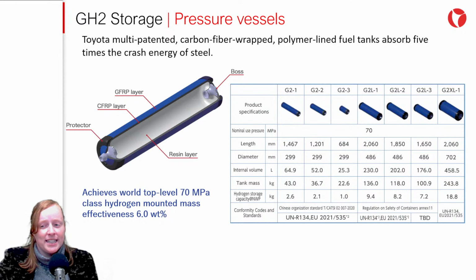It's interesting to see the 6% indicated in this specification. This is the mass of the stored hydrogen relative to the total mass of the system. Even in this case, which is highly optimized to minimize weight, the amount of stored hydrogen is a relatively small percentage of the total weight. Naturally, part of the added weight in this case comes from the protection necessary in the event of a crash. According to Toyota, it withstands a shock 5 times greater than that of a steel tank.